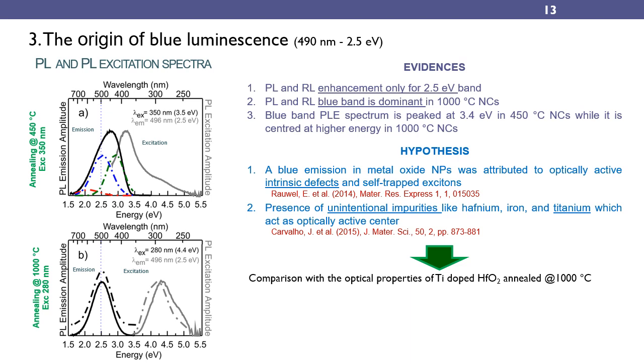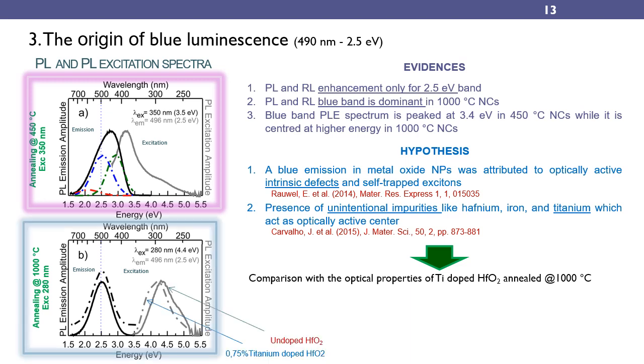Aiming at going deeper on the origin of the intense blue band of hafnium oxide, we studied the photoluminescence emission and photoluminescence excitation spectra of one sample of hafnia treated at low temperature, another sample treated at high temperature, and a third sample of hafnia doped with titanium and annealed at high temperature. The comparison of the excitation and emission spectra shows that titanium impurity is optically active only in the largest nanocrystals after the annealing and under high energy excitation.